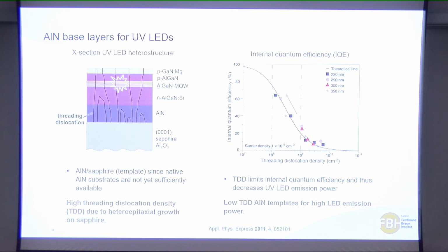So like I mentioned, why is the substrate, the template, so important? Like I said, we are growing on sapphire, which is transparent in the UV region, and if you grow aluminum nitride on it, because of the lattice mismatch, you're going to have defects in the crystal. And some of these defects bend out, but some of these defects continue into the LED structure and actually come into the active region, and there they act as traps, and then you will not have any light produced in the LED. And what you can see over here on the right-hand side is the quantum efficiency, again the efficiency of the device, based on the threading dislocation density, so the number of defects that actually go to the active region.